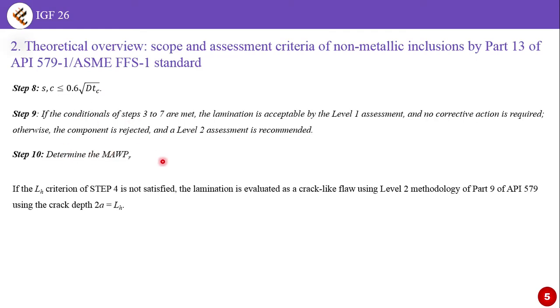Step 9, if the conditions of step 3 to step 7 are met, the lamination is acceptable by level 1 assessment and no corrective action is required. Otherwise, the component is rejected and a level 2 assessment is recommended. Step 10, the final step, is determining the reduced maximum allowable working pressure. It is worth mentioning that if the lamination height criterion of step 4 is not satisfied, the lamination is evaluated as a crack-like flaw using the level 2 methodology of Part 9 of the API standard, where the crack depth is equal to the lamination height.